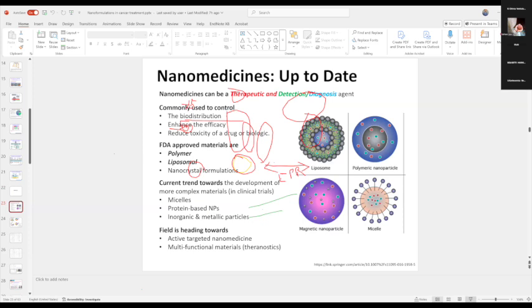Right now, the same molecule you can put into nanoparticles, in this case sodium carbonate based particles. Those will be quickly released into the bloodstream, and they can act in a much better way when you put this particular drug in them. Simply, you have not changed any drug, but you have improved the activity of the drug just by choosing a different type of nanomaterial.